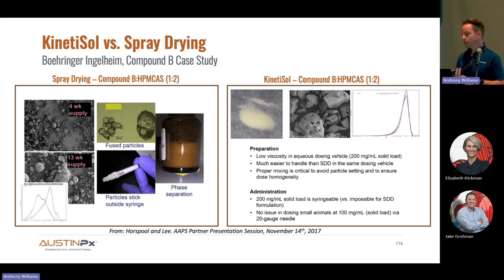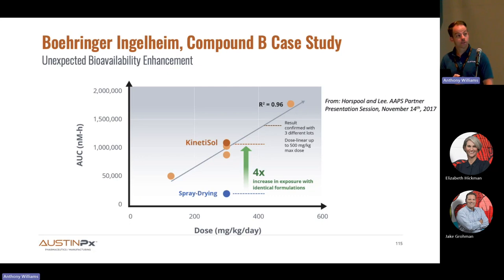So they came to us with some very practical needs: to ideally provide an intermediate that was more suspendable and gavageable, and to be able to manufacture at large scale to meet their timelines and their budget. And so the panel on the right is there to illustrate that we were able to tick all of those boxes. The KinetiSol intermediate typically has a bulk density between 0.5 and 0.6, which tends to be much better in terms of suspension and gavage dosing. We were able to manufacture a few batches for them at a fairly large scale and deliver it ahead of schedule. And I'm guessing at a little lower cost than what they were being quoted from spray drying companies.